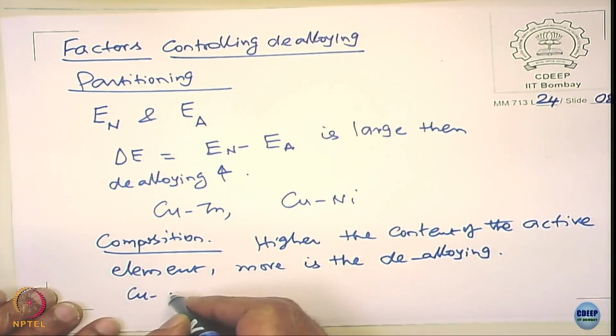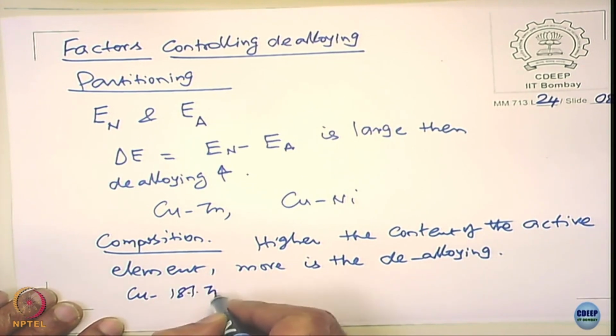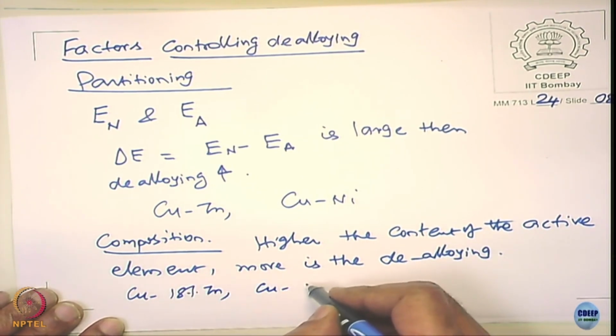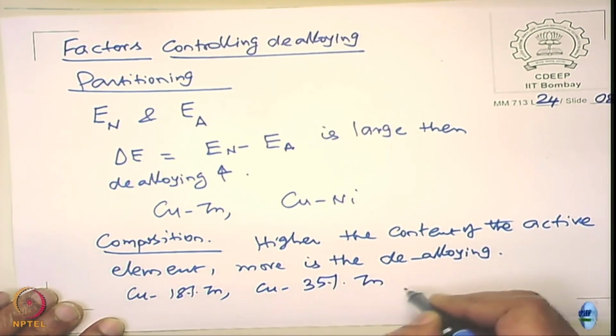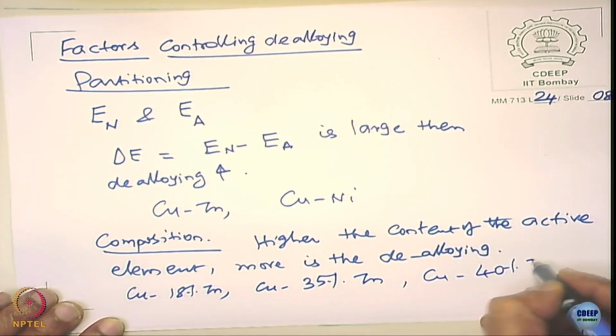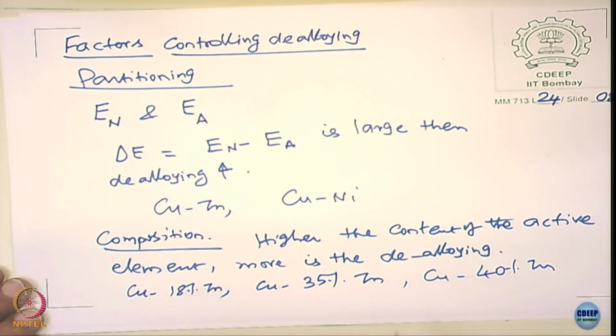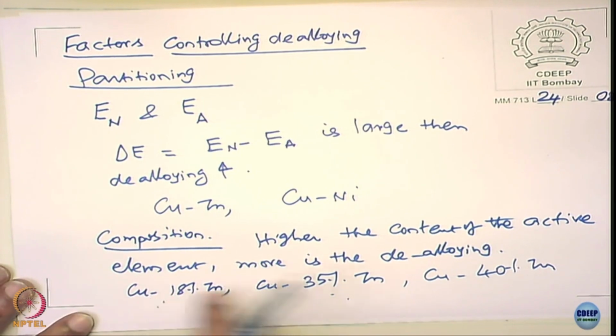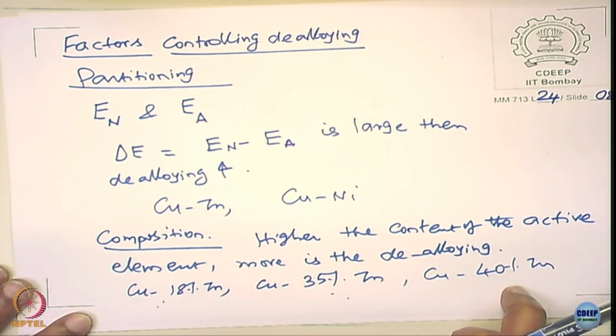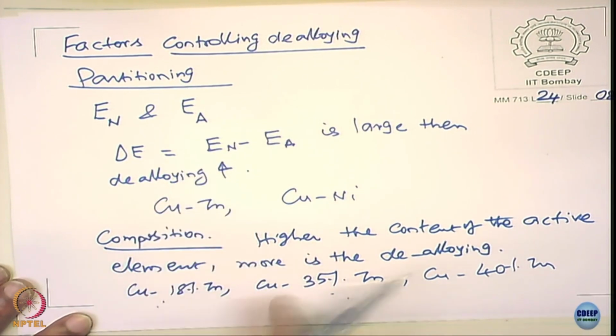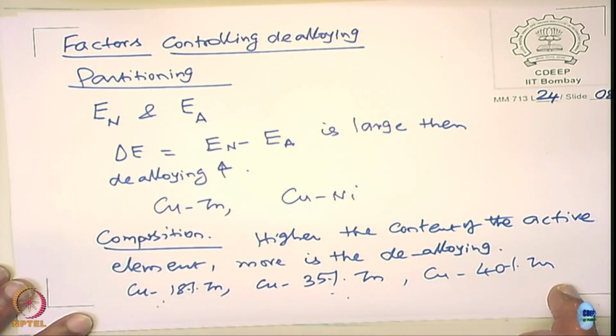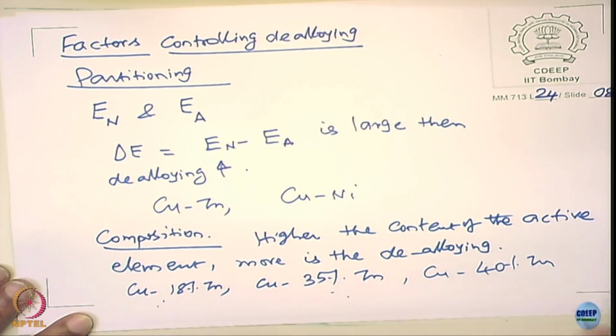copper, let us say 18% zinc, copper let us say 35% zinc, and copper 40% zinc. These both are called alpha brasses, and this is called the beta brass, the Muntz metal. The famous Muntz metal is copper 40% zinc. So, the dealloying will increase from this to this and to this, am I right? Because the delta E is going to be the same in all cases, but the content of the active element increases from this to this to this actually.